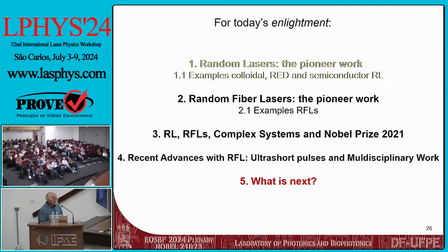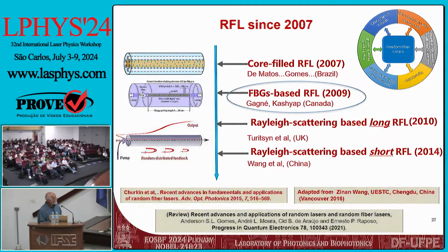Now let's talk a little bit about random fiber lasers. What you do is you have a fiber, and somehow you have a gain medium in the fiber. It can be rare earth doped ions. It can be the Raman gain, and you need some scattering. So the first demonstration was done in Recife by our group. What we did, we had a microstructured fiber with an empty core. We put the dye and the nanoparticles. We excited transversally and looked at the emission. I'll show a little more.